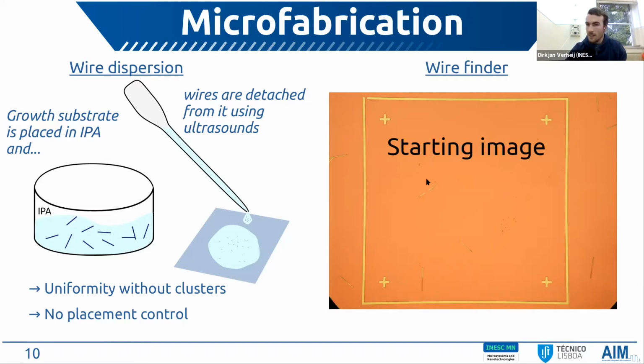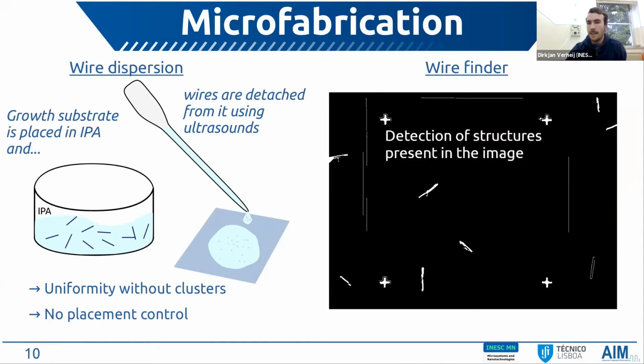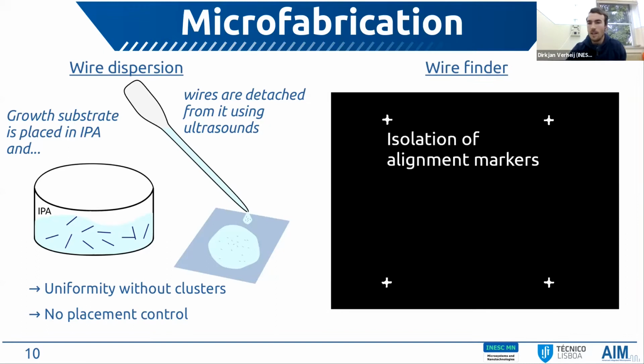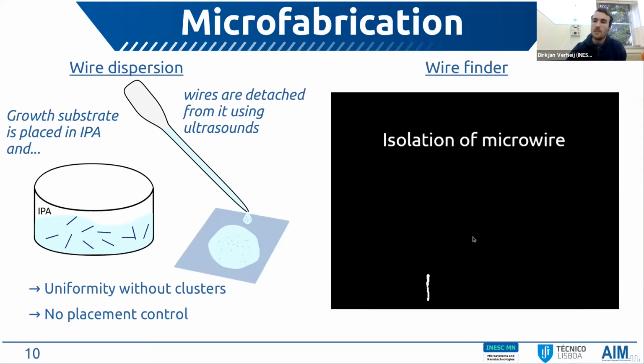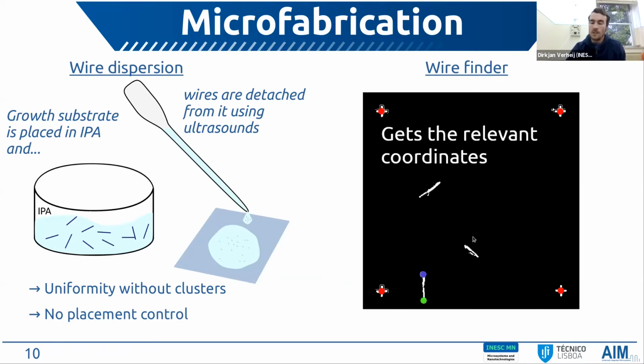So this is a starting image where we have here the 4 alignment crosses I talked about earlier, which act as references for the position on the device substrate, with several microwires dispersed. And then the software basically detects the structures present in the image. So we have the 4 alignment markers and 1 of the microwires present in the image. And it gets the relevant coordinates. And as we can see here, it even can distinguish between the P part of the wire and the N part of the wire, because of the increased thickness of the P part.